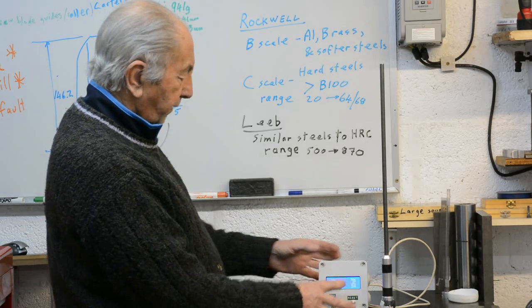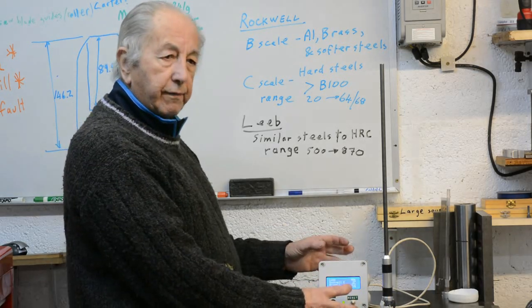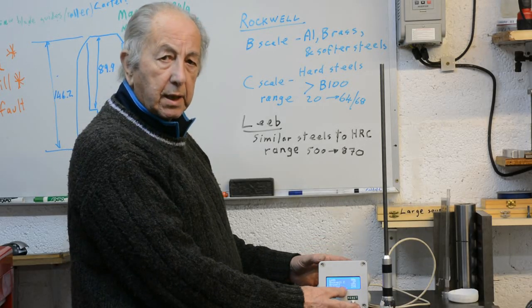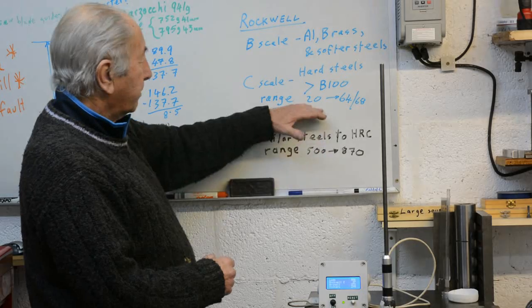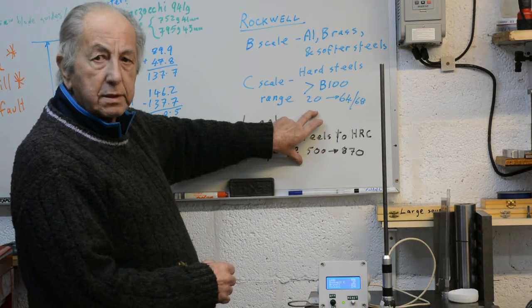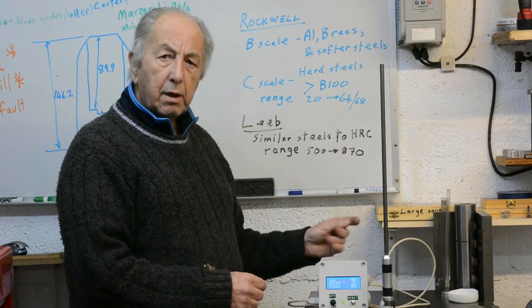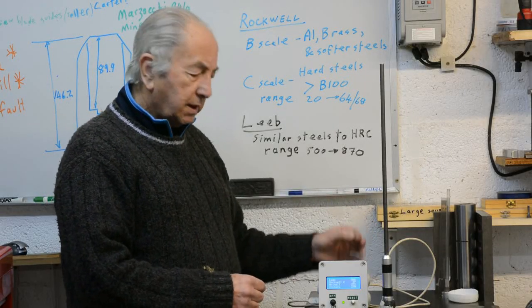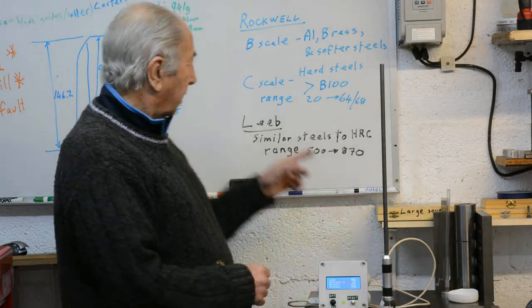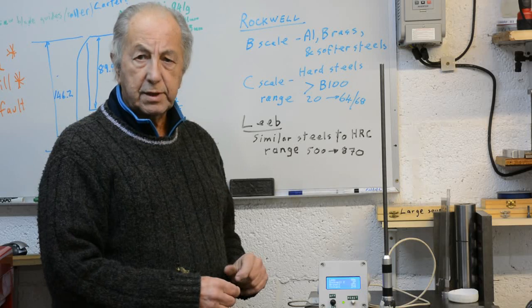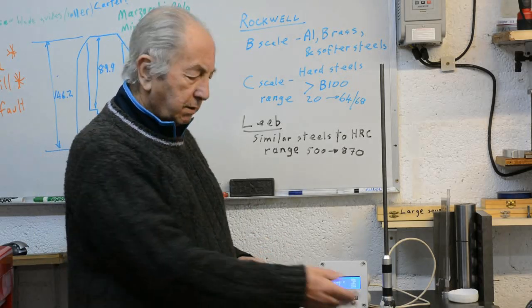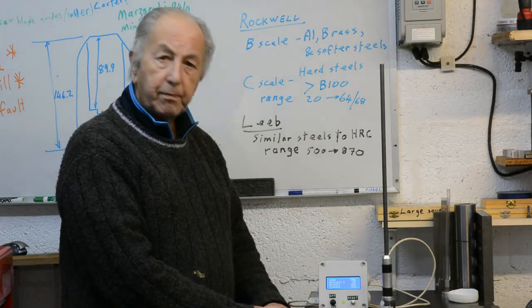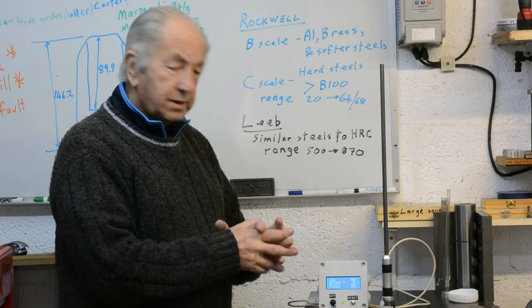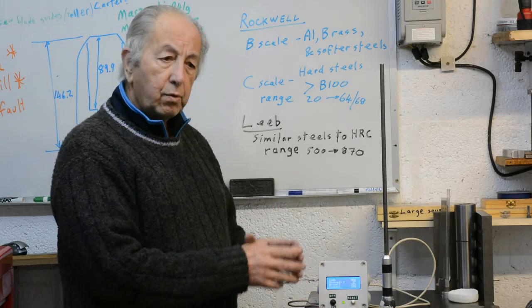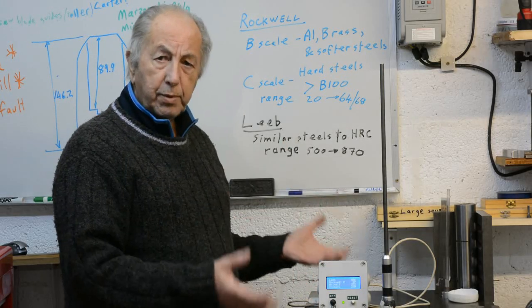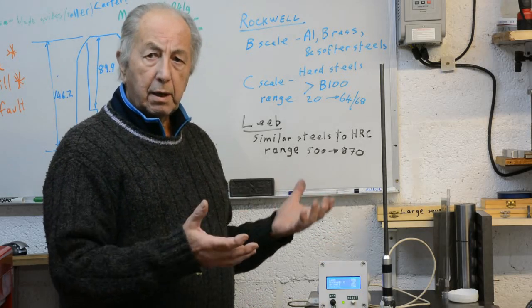We've now got a value on our Leeb scale of 556 and on the Rockwell C scale 27. Now both of those numbers fit within these ranges of hardness, but it doesn't comply with hardness standards because we're measuring aluminium on scales that are meant for steel. For our purposes it doesn't matter. I could put another block of aluminium here that was softer and it would tell me that it was softer. It's still quite a useful tool, even though we need to consider the scope in which we're using it compared to the scope of the standards.